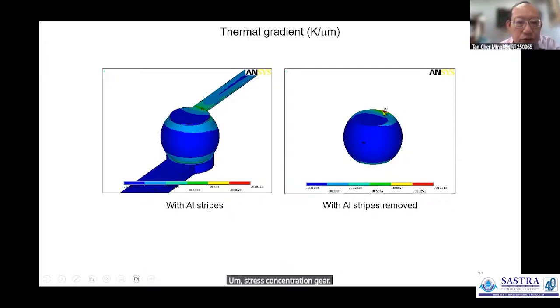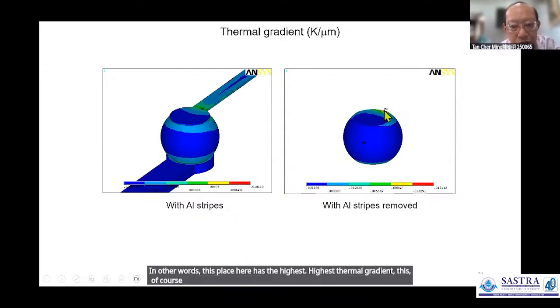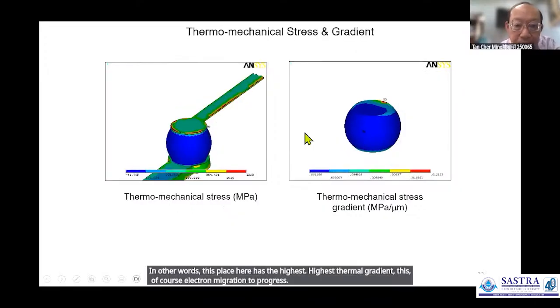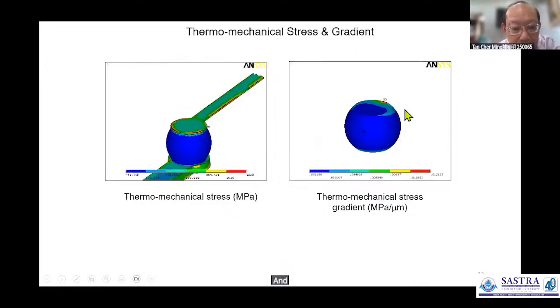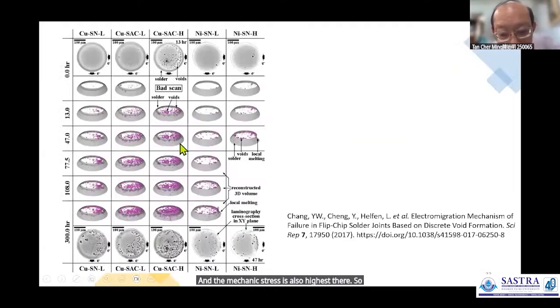This stress concentration is due to the thermal gradient. In other words, this place here has the highest thermal gradient. This will cause the electromigration to progress, and the thermomechanical stress is also highest there. So this is experimental work that people have done.